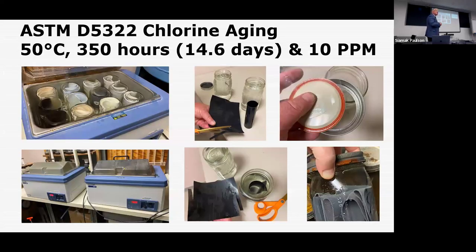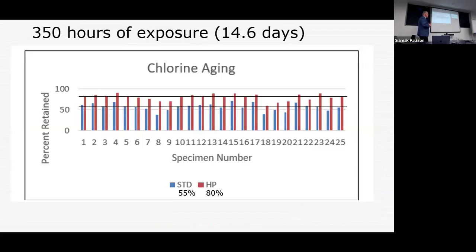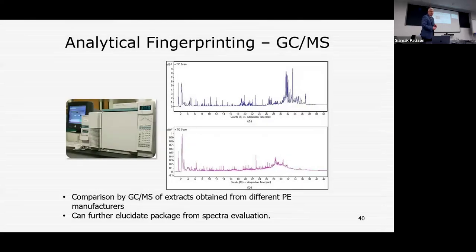The next, which is not akin to GM13, is chlorine. Chlorine is only run at 50 degrees C. For those who remember chemistry, it's a halogen. It's an aggressive material to any olefin, and it is at a 10 ppm solution. Again, in the series of data here, you can run standard and high pressure. And again, it works very well if you look at 8, 18, and 25. So we have a way to challenge this material on a short-term basis quite effectively.